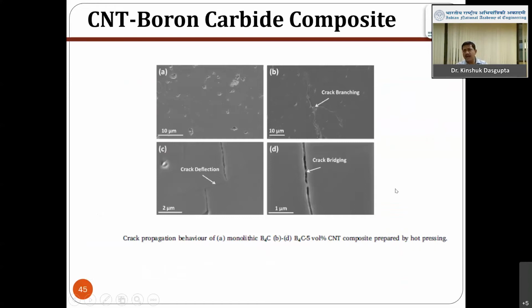Then I'm just discussing how it improves the fracture toughness. This is without carbon nanotube. If we see, this is the crack which is through and through. This is a through and through crack. But when you add carbon nanotube, the crack gets branched, or there is crack deflection or crack bridging. These are the methods by which you absorb the energy. So you are improving the fracture toughness. That means more and more energy is required for the crack to propagate, and that is required for application, for ballistic kind of application.